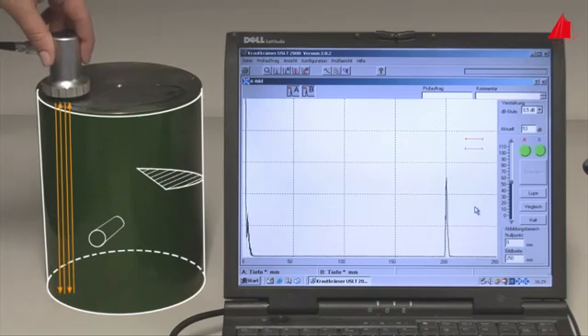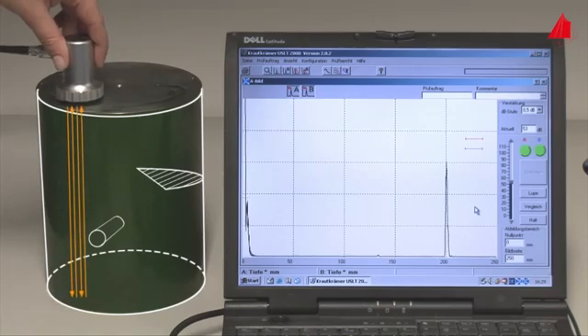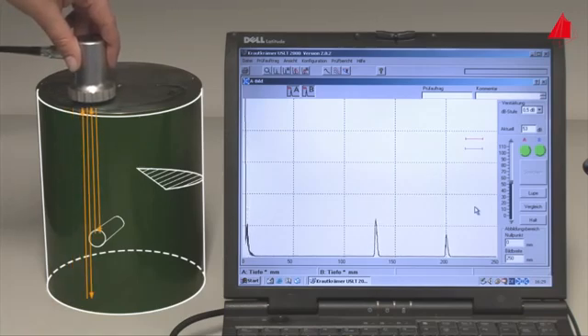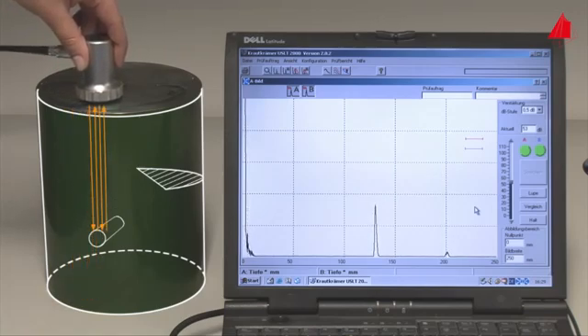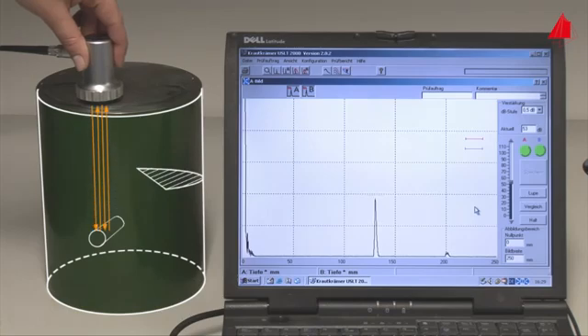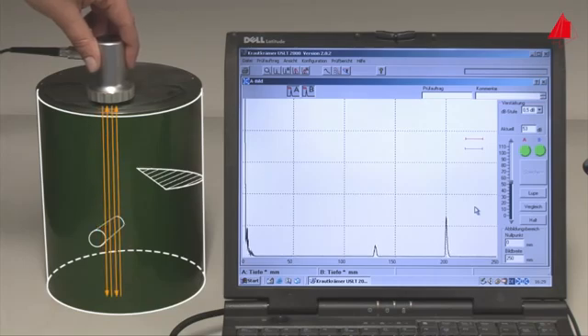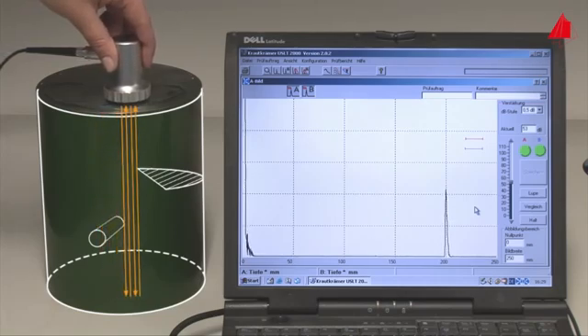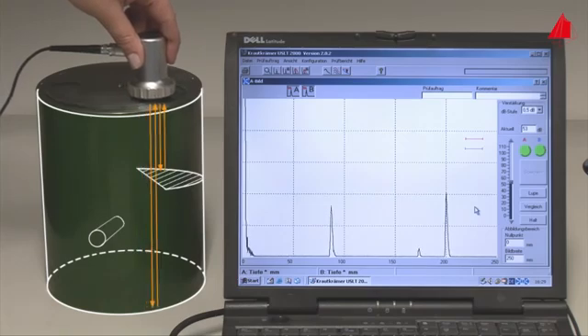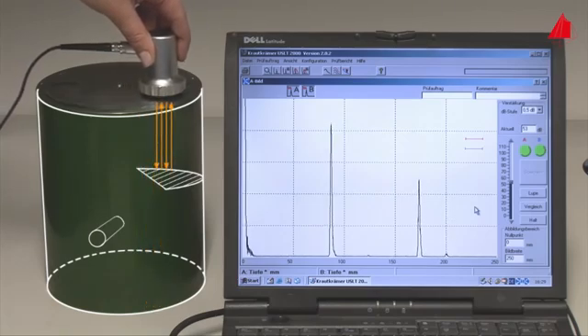And these are the defects: a drill hole and a saw cut, filled up near the surface and painted—they are not visible from the outside. The drill hole in a depth of 130 millimeters. The saw cut 87 millimeters below the surface.